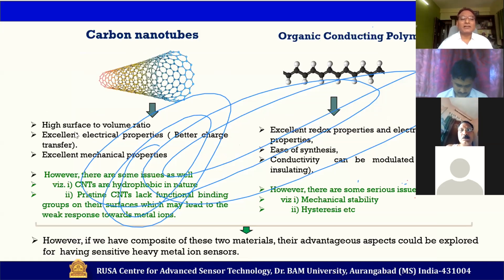Carbon nanotube has a very high surface to volume ratio, because this is a nanostructured material. It has excellent electrical properties, excellent mechanical properties. However, there are some issues as far as heavy metal ions are concerned. One of the critical issues is that CNTs are hydrophobic in nature. This is going to be one of the problems whenever you are using them in aqueous media. And moreover, pristine CNT lacks functional binding. That is also going to be an issue, because if you really want to functionalize the CNTs, there will be some limitations. It's not like you cannot do it, but there will be some limitations.